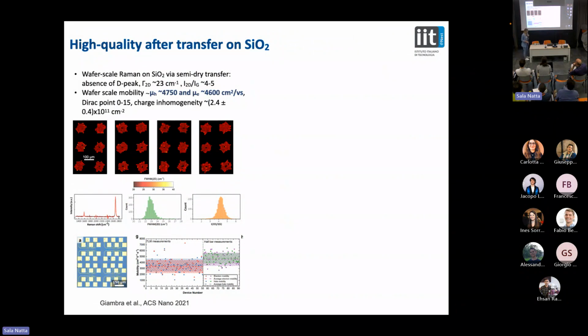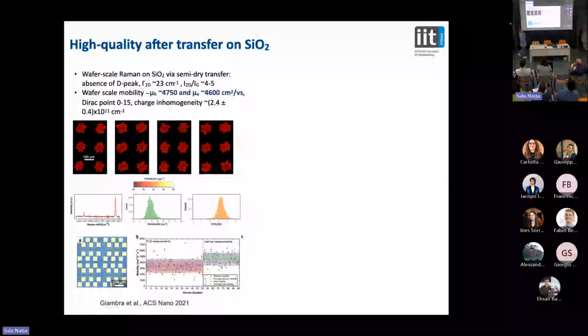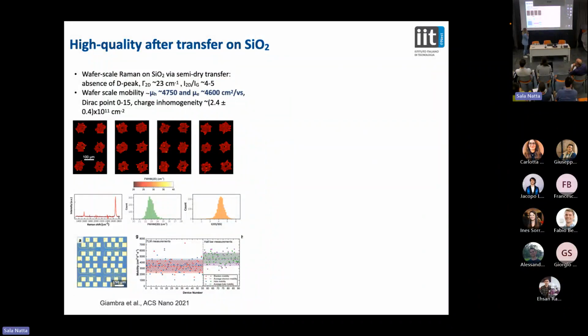When you transfer on top of different substrates, you always have to make sure that the material preserves integrity as a first thing, and quality, of course, if you're really aiming at high quality applications. So for example, we look with Raman spectroscopy, which is a very common tool for people working in material science, and is capable of giving you an idea of the presence, quality, and defects of your material. Here we were mapping, and the color scale tells us the width of a specific peak that tells us how much strain inhomogeneity we have in our material. In this case, we see a really, really minimum value. That means little strain inhomogeneity. That means really good transport, because if you have a lot of strain inhomogeneities in your 2D materials, your electrons will not move as fast as you want.